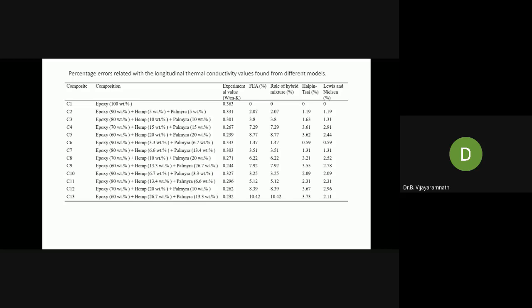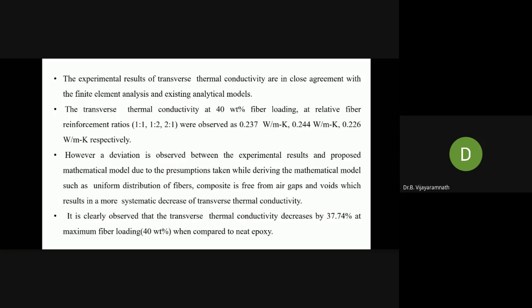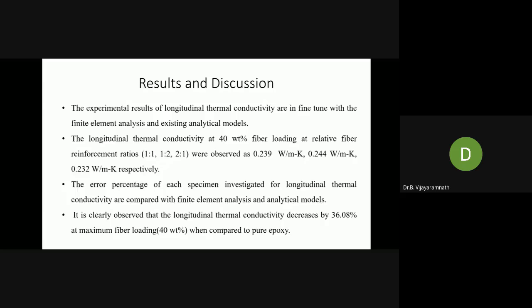Similarly, in the case of transverse thermal conductivity, we observed at the same fiber loading percentage of 40 a value of 0.226 watt per meter Kelvin. So from both the results it is clear that the conductivity decreases by 37.74% in the case of transverse thermal conductivity, and similarly around 36.08% while evaluating along the longitudinal direction, that is parallel to the fiber.